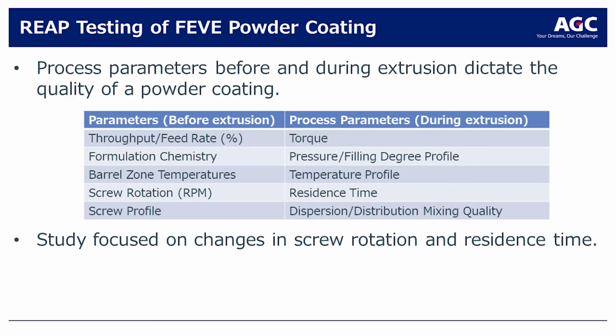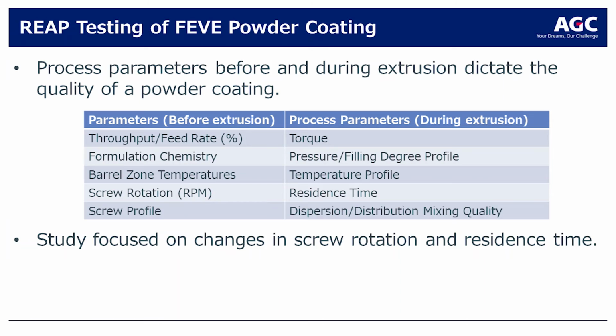The parameters, what you're looking at is what influences the properties of the coating. Well, certainly the feed rate does. In other words, how fast is that powder moving through? The formulation chemistry, obviously the paint itself is going to have an influence on that. You can do different barrel zone temperatures as this material is going through the barrel of the processor. You can raise or lower temperatures. You can change the mixing and things like that. Screw rotation, RPM, affects the residence time. And the screw profile gives you better dispersion under certain conditions. So this one focused on changes in rotation and residence time. We just picked two of those and ran with that.